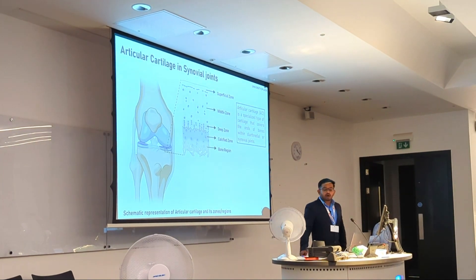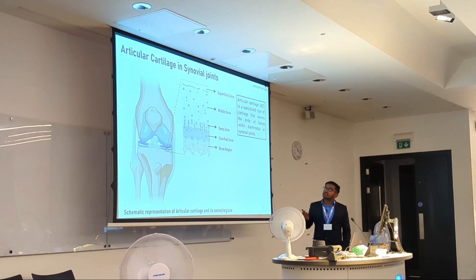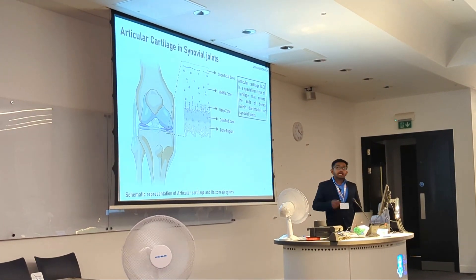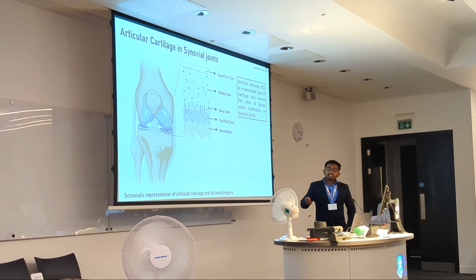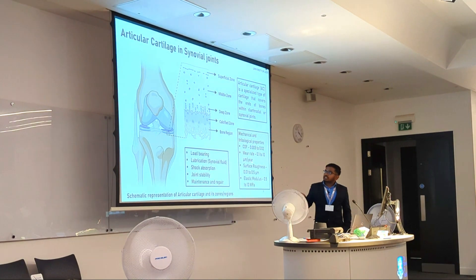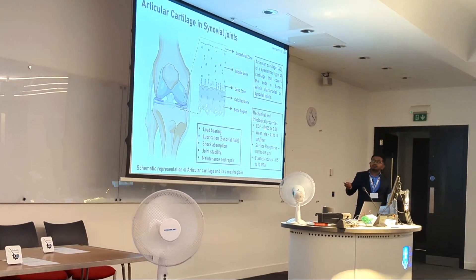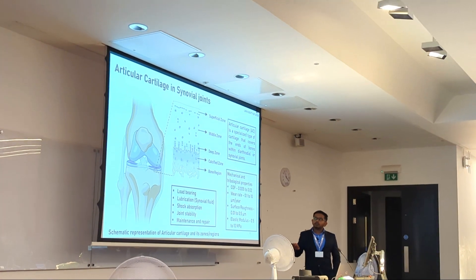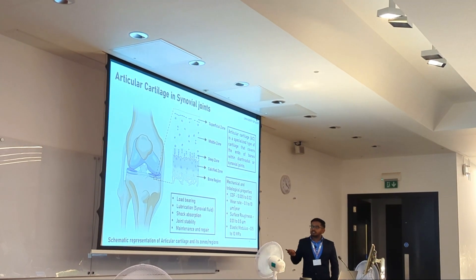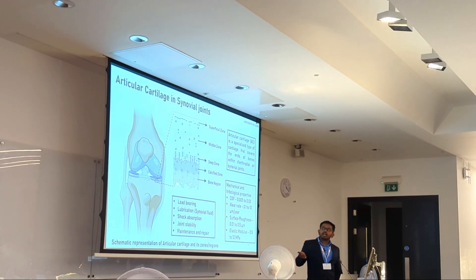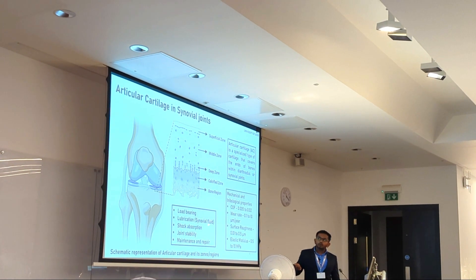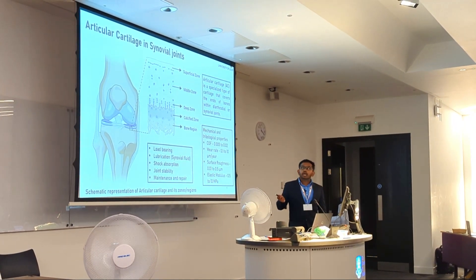Articular cartilage is one of the most remarkable tissues in diarthrodial joints, as it provides nearly frictionless movement. The coefficient of friction of cartilage surfaces is approximately 0.005, the wear rate is 0.1 to 10 micrometers per year, surface roughness is 0.01, and the elasticity modulus is 0.5 to 10 megapascals. The main functions of cartilage are load bearing, lubrication, shock absorption, joint stability, and maintenance and repair.